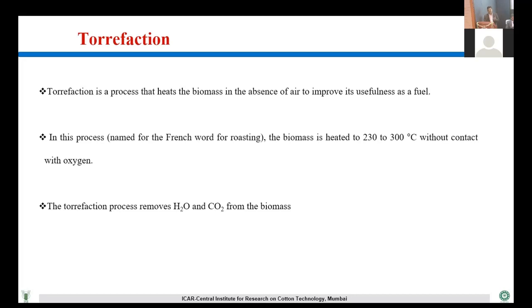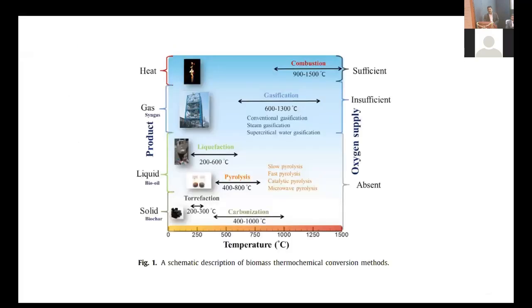So the government is coming up with a lot of technology. One of the technologies the government is thinking of is torrefaction. Torrefaction is found to be a very good solution to the issue of biomass-based energy. Torrefaction is a very simple process. We have different temperature processes, carbonization and pyrolysis. It is a mild pyrolysis. We just heat the material between 200 to 300 degrees Celsius for 30 minutes to 1 hour.